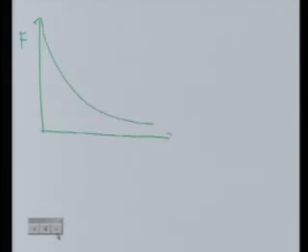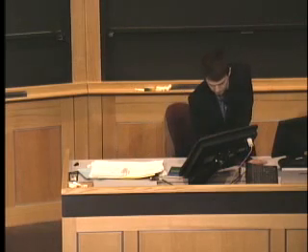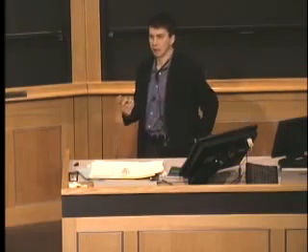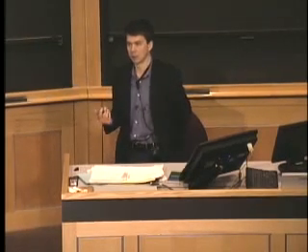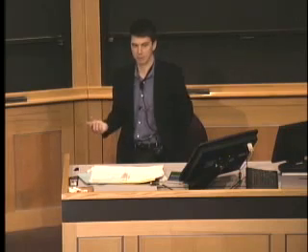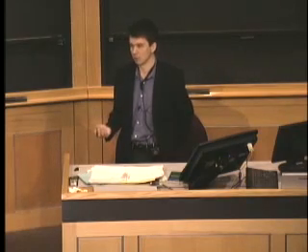If you have an embedding function as a function of rho, and you're working at this density, say the density of the bulk, and you're studying bulk problems, you could take the slope of this, take the linear term, make a linear approximation to that, and add that to the pair potential, and now you wouldn't have to worry about the embedding function. So at constant density, pair potentials are actually pretty good.